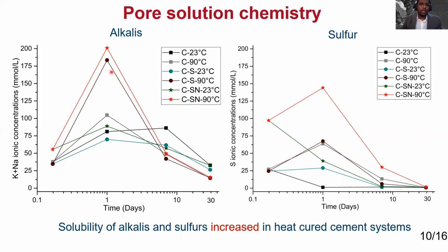some differences. For example, for the 4% sulfate and the 1% alkali expansive mortar, the alkali dissolution is the largest. Correspondingly, if we look at the sulfur dissolution, we couldn't see much difference in the low sulfate, low alkali mortar when comparing with the mildly expansive 4% sulfate mortar. We couldn't see much difference in the sulfur dissolution.